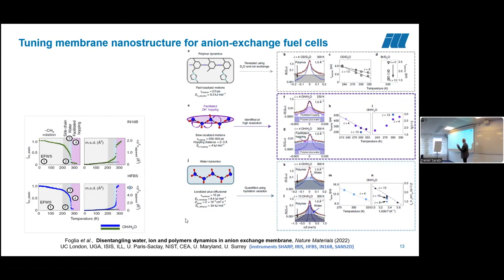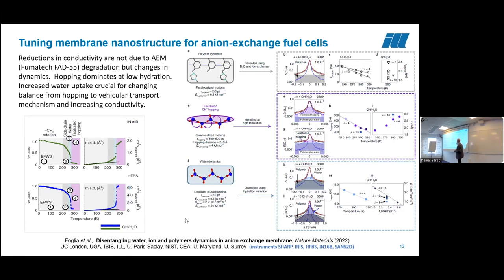Really complex story. The key message is they were able to confirm the reductions in conductivity of those cells. It's been thought in the past that hydroxyl ions chemically degrade the membranes, but they were able to show that reductions in conductivity are really associated with a reduction in dynamics, not chemical degradation of the membranes. But they were able to show that at very low levels of hydration, hopping dominates. And as you increase the water uptake, bulk water dynamics takes over and vehicular transport takes over. In other words, hydroxyl ions being carried along with groups of water hydrating them.